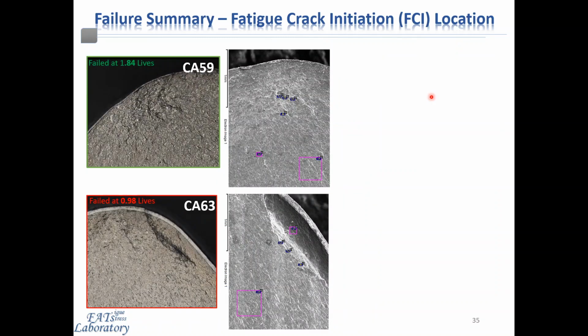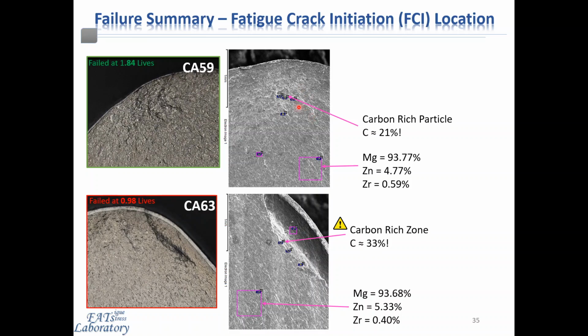Under SEM, we observe the area and the matrix away from the initiation site to have a chemistry almost identical to the manufacturer's published chemistry for ZK60, which was the alloy that was being investigated for these particular forgings. When we looked closer to these faceted regions, we see evidence of a number of carbon-rich particles with poorly fused fold lines surrounded by a carbon-rich zone. So we can see that here.